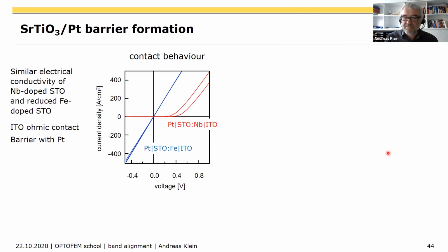Okay, there was a question about oxygen vacancies, but maybe I can skip that. Well, I take it. It's a good thing. We made diodes. One contact was ITO. It's an ohmic contact to strontium titanate, and we made platinum, which is a barrier. And we compared niobium doped strontium titanate, and we did also an iron dope, which is an acceptor doping, which is usually an insulator. But we reduced the iron doped strontium titanate so that it becomes almost as conductive as the niobium doped one. You see, this one doesn't show any barrier, but only the niobium doped one really shows a rectification.